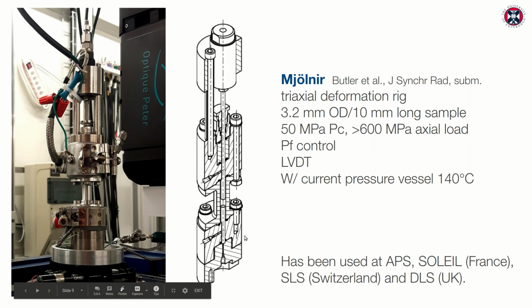There's a bottom platen here, there's a pressure vessel here, which is the X-ray transparent bit, and there's a top platen, and then up here there's also now an assembly with a hydraulic ram, which you can see up here, which drives a piston. And this now allows us to establish a triaxial stress state. Actually it's a biaxial stress state, because sigma 2 and sigma 3 are the same. This is a deformation rig. It can also take 3.2 millimeter OD cylindrical samples, same length.